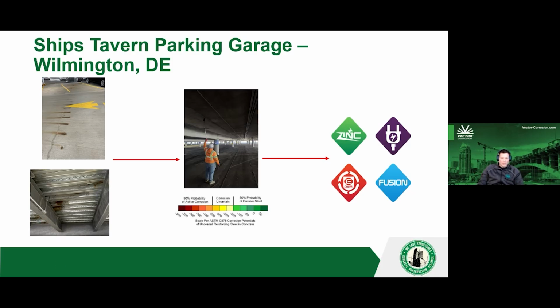So VCS Durability was brought out due to a half cell potential survey, which found that there was pretty widespread corrosion activity going on in this garage, and something needed to be done. But one thing to note is that the concrete's actually in relatively good shape, but because of the way the steel pan decking is, a lot of the water and moisture making its way through cracks and through pores just sits on it and is essentially eating away at the structural pan deck.